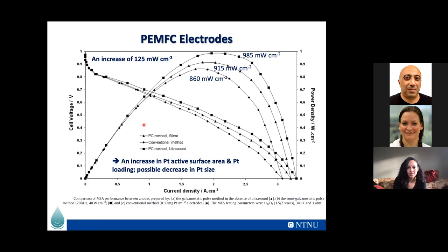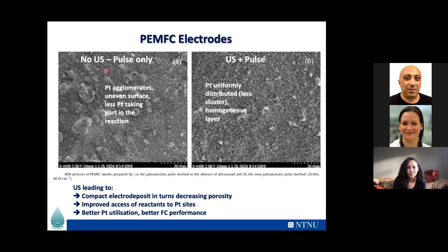So this is an SEM image here. You can see that with no ultrasound, we're pulsing only galvanostatically, so you get platinum agglomerates and an uneven surface, but using ultrasound, your surface is more uniform. Okay, we get a better fuel cell performance.